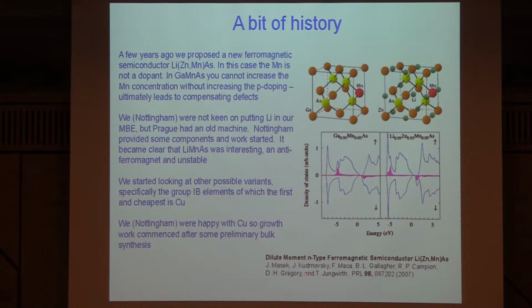But fortunately, Vit had essentially a redundant machine that he was prepared to sacrifice. So essentially we sent him some bits and he started growing zinc lithium manganese arsenide. Unfortunately, now, I don't want to worry you theorists, okay? But it's not always possible to take atoms and just put them in appropriate lattice sites, okay? Nature doesn't always want to play that game, and unfortunately, definitely didn't want to play that game with lithium zinc manganese arsenide. So fighting with both lithium and zinc was really difficult.